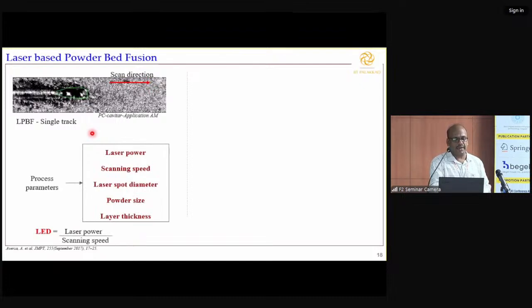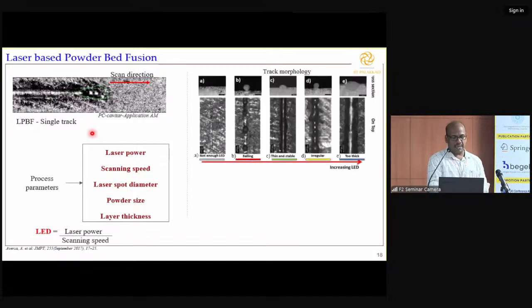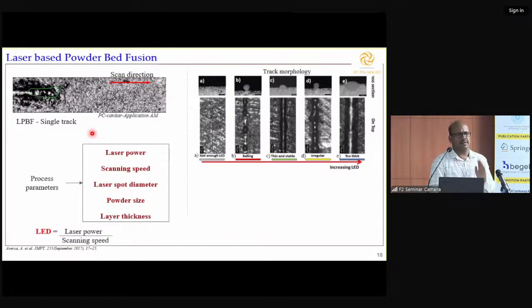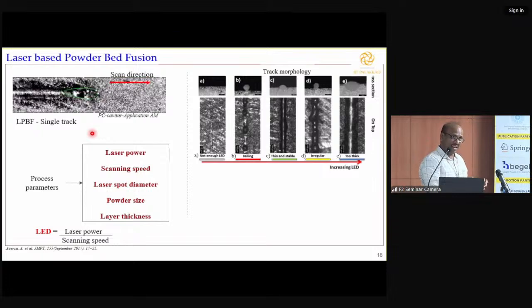These are the process parameters generally used for laser powder bed fusion: laser power, scanning speed, laser spot diameter, powder size, and layer thickness. The combination of laser power and scanning speed gives laser energy density. What is the role of laser power and scanning speed? Consider this a laser source, say a 1 kilowatt laser, for example. Then I'm slowly moving like this. This is scanning speed. I'm going slowly, whereas another time I'm going very fast. Now, each and every particle, based on the scanning speed, will get a different amount of energy. I hope you're able to understand that.